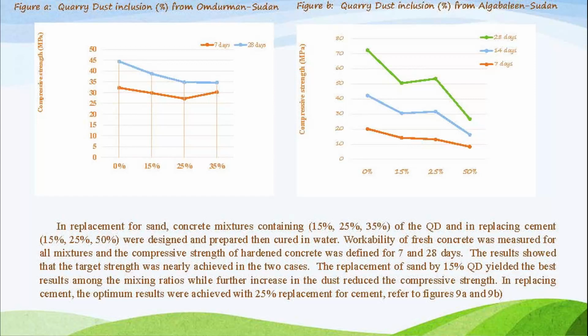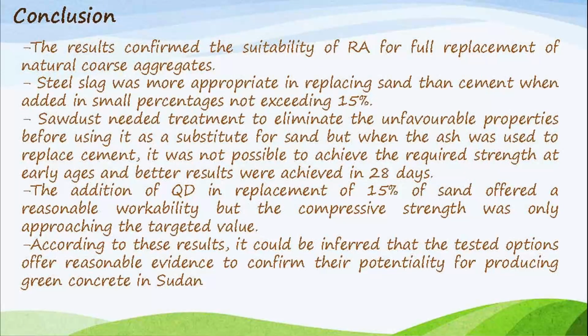Concrete mixes containing 15, 25 and 35% QD replacing sand, and 15, 25 and 50% QD replacing cement, were designed and prepared. The workability of fresh concrete was measured for all mixes, along with compressive strength. The replacement of sand by 15% QD yielded the best result, and for the replacement of cement, about 25%. The results confirm the suitability of recycled aggregate for full replacement of natural coarse aggregate. Steel slag was more appropriate in replacing sand than cement when added in a small percentage, not exceeding 15%.